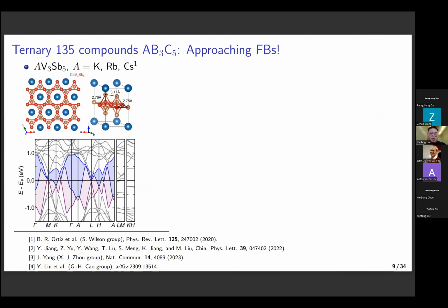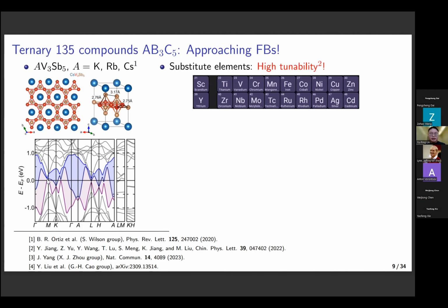In addition to the binary materials, the ternary 135 compounds have been extremely popular in the past few years. These compounds usually have the AB3C5 structure, and one of the most classic examples is AV3Sb5. In this material, the vanadium atoms form a kagome network, and in the band structure we can see that the vanadium kagome network contributes to the kagome band. For the vanadium-based materials, the Fermi level is at the Van Hove singularity of the kagome band. However, it has been shown that these 135 materials have very high tunability by substituting the elements.